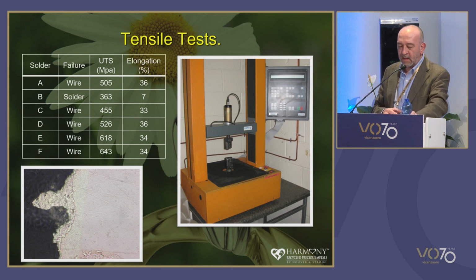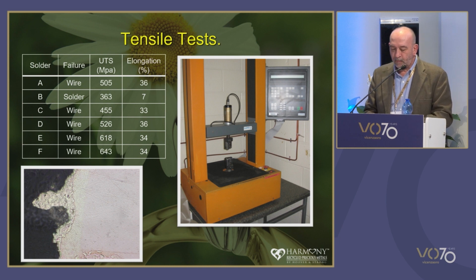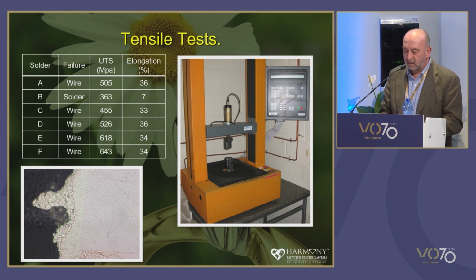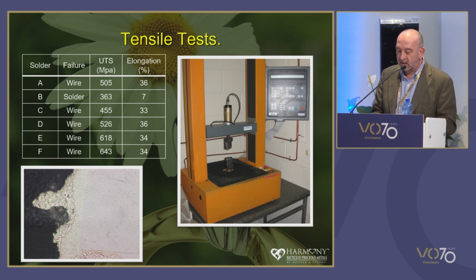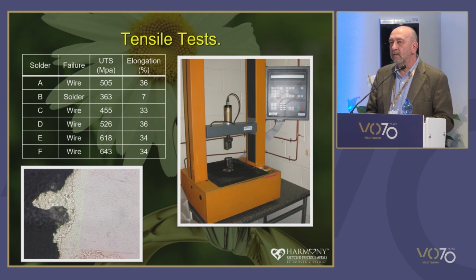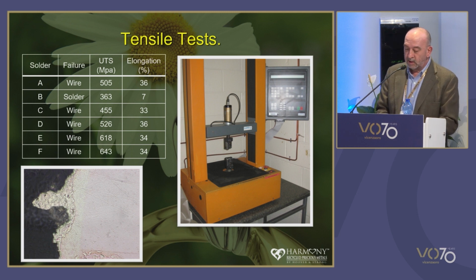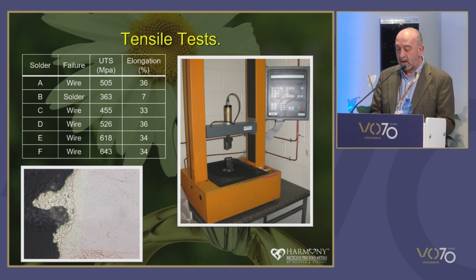So a quantitative measure of the strength of a solder and the solder joint can be determined by butt joining two pieces of ground wire together and then performing a simple tensile test. The important factor here isn't so much the numbers, but whether the sample fails at the solder joint or whether it fails in the wire. If it fails in the wire, the solder joint is at least as strong as the parent metal.